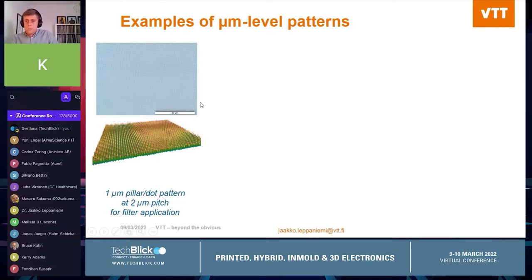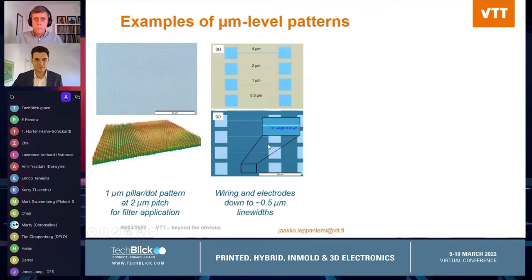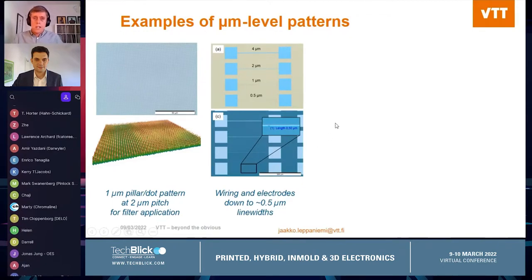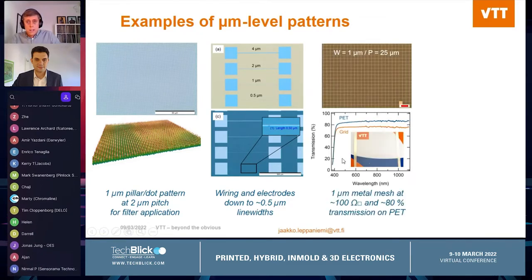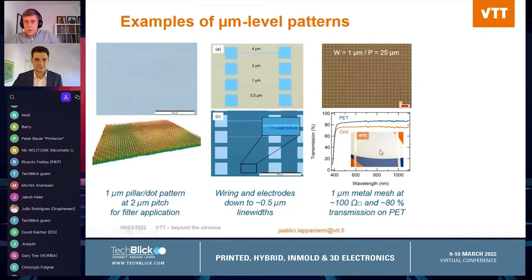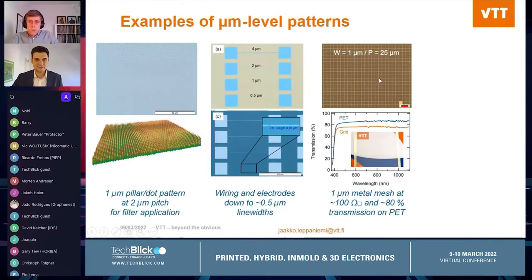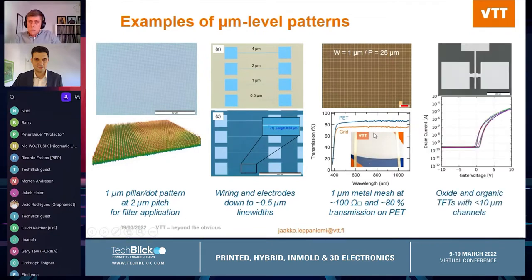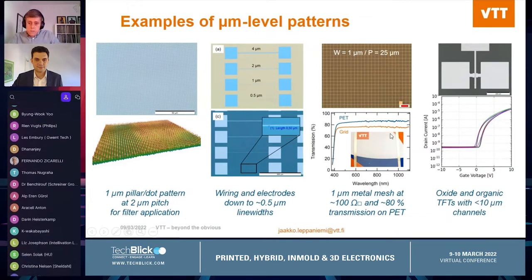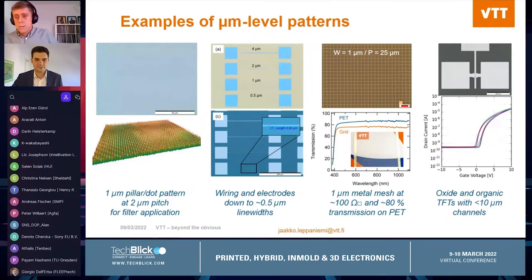Here are some examples of micrometer level printing using our reverse offset printing system. On the left side, we have a 1 micron dot array printed for filter application. We can also fabricate isolated wirings and electrodes down to 0.5 micron resolution. Here you can see a PET foil with transparent metal mesh conductor with 1 micron line width and good transmission in the visual range. And also oxide and organic TFTs with feature sizes below 10 microns are enabled by this high overlay accuracy at micron level.